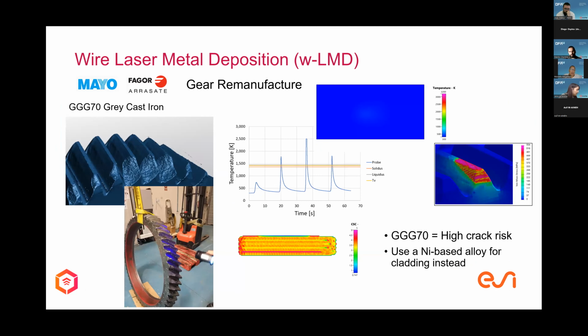Then finally, we look at the gear of a very large application. You see the gear size as compared to the components in the background. It's a very large component with a lot of damage on certain corners, which were scanned as presented by Sarah at the beginning. The gear was cast using a gray cast iron, which has been used for several times. So we were concerned about how the material absorbed different impurities and how it will behave once we deposit new material on top of it.